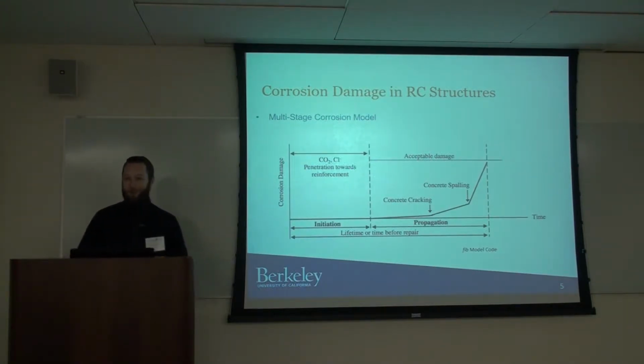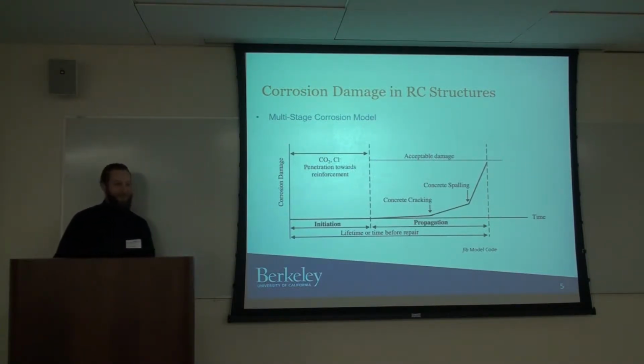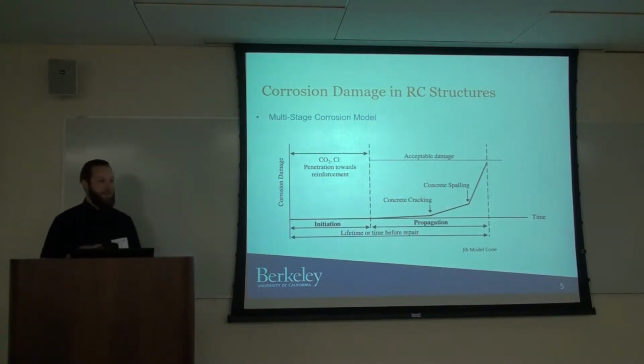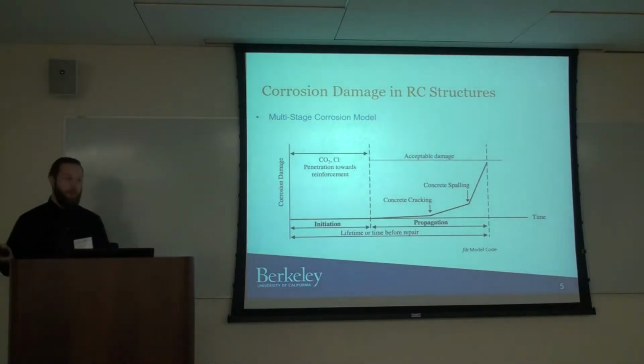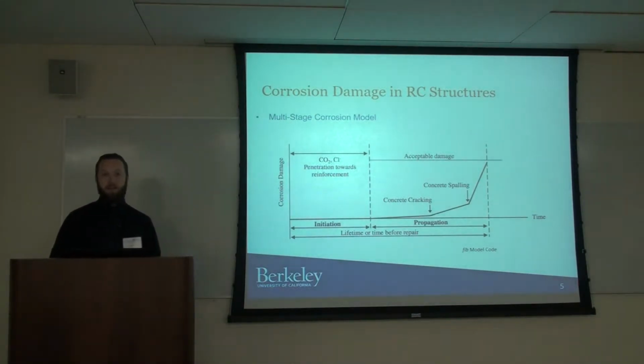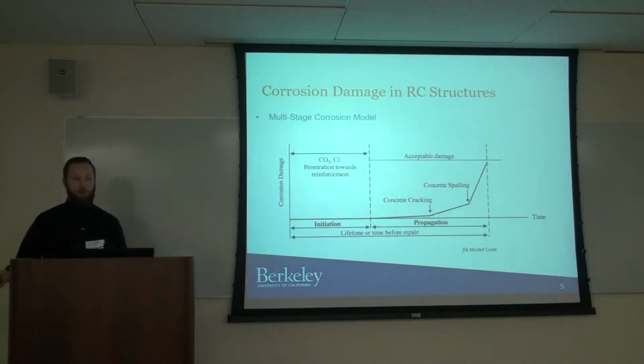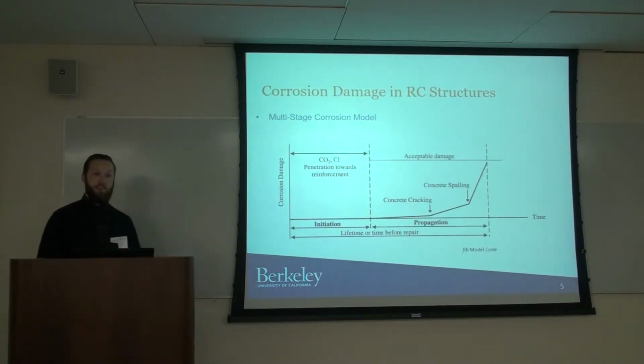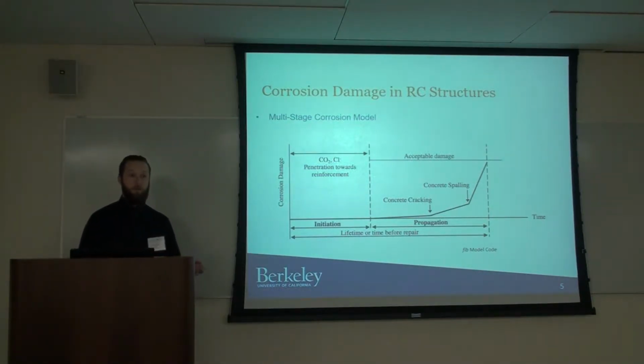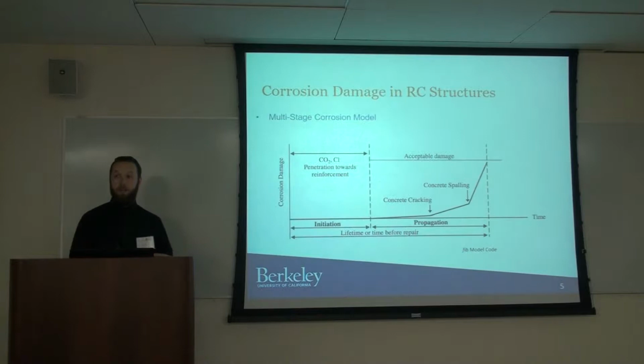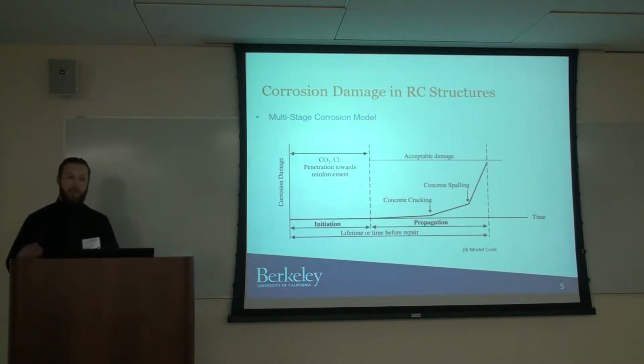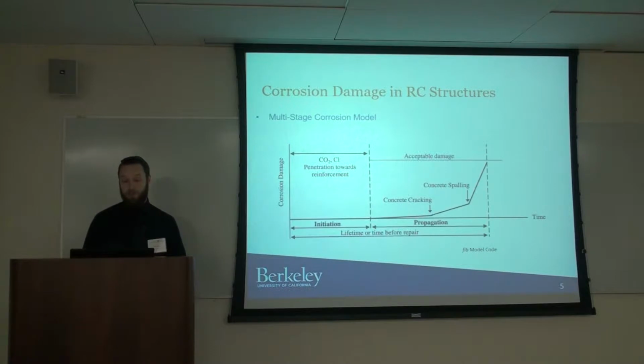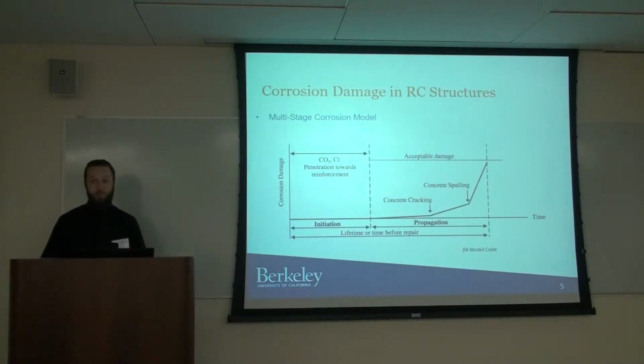So I know this isn't a corrosion conference, so I'll try and get into the hybrid simulation aspects, but briefly I just want to touch on a little background. The corrosion process in reinforced concrete can be broken down into two stages. You have an initiation period where the reinforcing steel is passive due to the high pH of concrete. And during this period, aggressive agents like carbon dioxide from the atmosphere or chlorides from seawater or de-icing salts are penetrating into the concrete cover and will eventually depassivate the reinforcing steel, which would take us into the propagation stage,